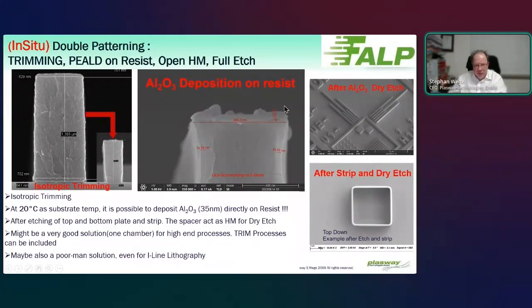And in the next step, we remove here with an ALE step the top plate of the aluminum oxide, also the bottom plate. We can even then strip the resist, and at the end of the day, you have this structure, and this structure is in the order of 50 nanometer in this case, and we can use this aluminum oxide directly as a hard mask. Everything can be done in one chamber.